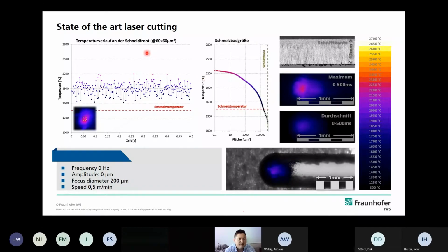In this diagram, you see the time on the x-axis, and on the y-axis the temperature measured in this process zone on the cut surface, on the cut front. And this is the result of the cut. You see there's a little bit of dross on it, but we also use quite low laser power, that means 3 kW, and we try to achieve a quite good cut. What we can see in the diagram is that the energy or the temperature is in a quite small band, and every time about the melting temperature of the material.